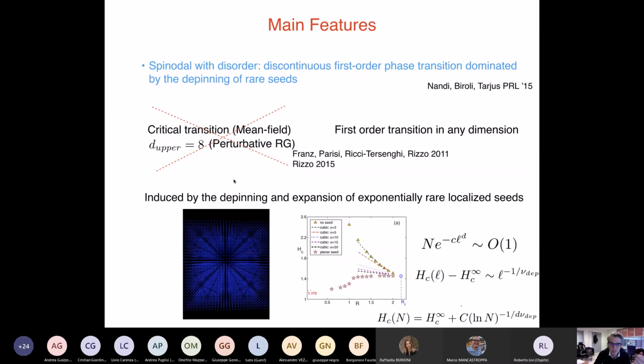And what happens, the physics of this transition is related to the fact that you have very rare, well, let me show you actually the movie first. So the blue are the minus spins and the red are the plus spins. And this is what happens when you have this spinodal transition and you do a discontinuous jump. What I'm showing here is that I'm changing the field very, very slowly, and I'm just looking at the movie of the three-dimensional random field Ising model, looking at the behavior of the spins.